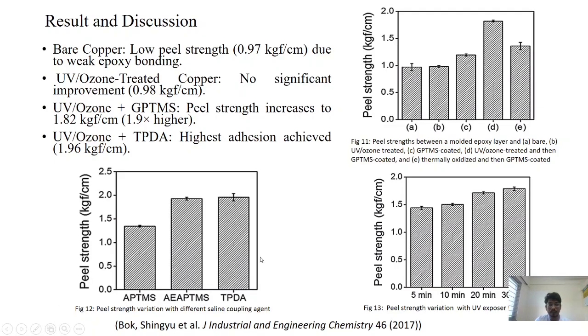which is showing the variation of different coupling agents with the peel strength. In this graph, TPDA, which is a silane coupling agent, has the highest peel strength as compared to all, because it has a hydroxyl group which promotes better bonding between the copper and epoxy layer. And now figure 13 shows the peel strength variation with the UV exposure time. As the UV exposure time increases, like 5 to 10 minutes, 10 to 20 minutes, and up to 30 minutes, the peel strength also increases, because when the UV exposure time is increasing, the copper is more oxidized to copper oxide and copper hydroxide, which forms a greater bond between the copper substrate and the epoxy. So that's why the peel strength is increasing as the exposure time is increasing.